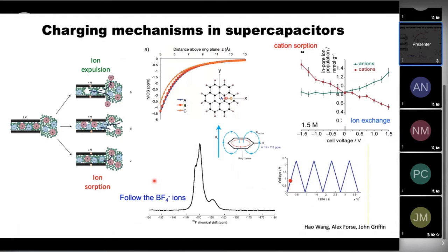And so what we did was to modify our in-situ device so that we could follow the ions going in and out of the supercapacitor carbons. And so this is now the fluorine NMR of the BF4 minus ion going in and out as you're charging up the electrode positively and negatively. And so this is the signal of the ions that are going in and out of the pores.